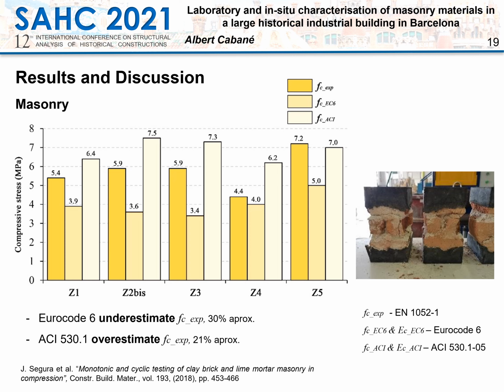The characteristic compressive strength of the masonry has been evaluated from the experimental averages and the empirical equations provided by Eurocode 6 and the American requirement for masonry structures. As observed in the graphic, Eurocode 6 provides the lowest values, while the American requirement results are higher than the experimental ones. Previous research at UPC provided a good relationship between the empirical and experimental strength for masonry with lime mortars over 2 megapascals strength. This good relationship has not been found in this research, developed with low-strength lime mortars. In these cases, masonry samples have a lime mortar compressive strength between 0.3 and 1.3 megapascals.